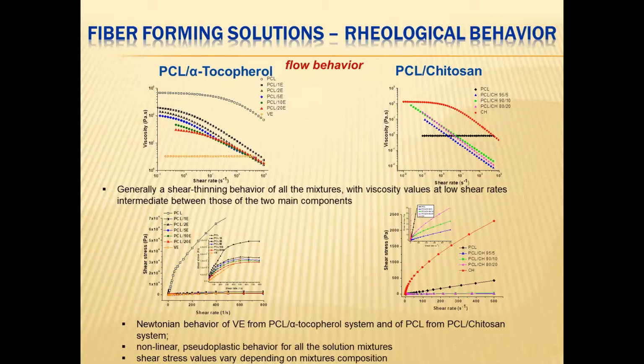The flow behavior investigation showed a generally shear thinning behavior for all the mixtures prepared, with viscosity values at low shear rates that are intermediate between those of the two main components. For the PCL alpha-tocopherol system, Newtonian behavior of vitamin E on the entire shear rate range is observed, while PCL presented shear thinning behavior with Newtonian plateau up to a critical shear rate.